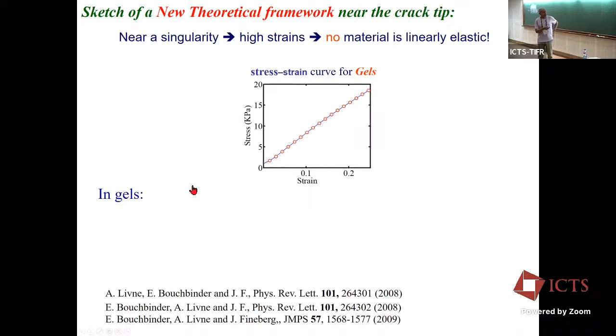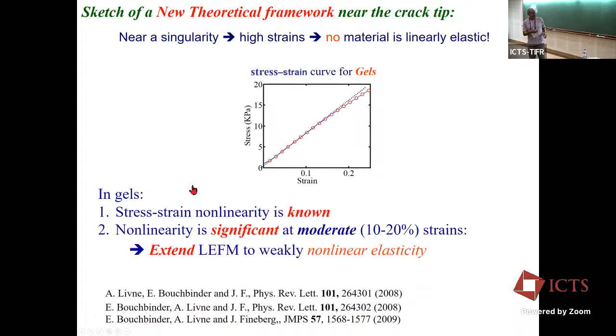So in gels, we can measure the stress strain curve, and it looks kind of linear. These are the gels that we're using. If you wake me up at 3 in the morning and ask, is that a straight line? I would say, yes, go away. But if you do it carefully enough, you find that at strains of about 0.1 or so, the stress strain law, which for neo-Hookean materials is what it actually should be, does deviate from linear elasticity. A small deviation. So what?